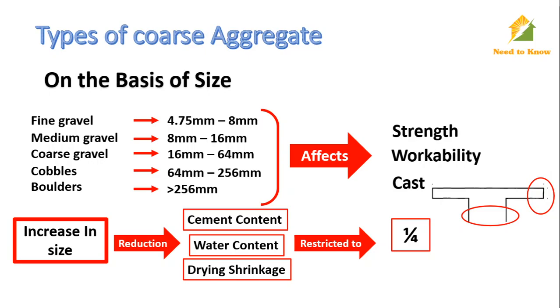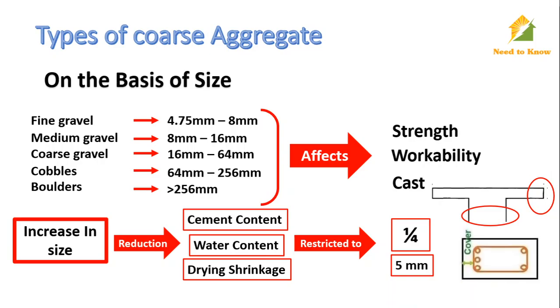The size of the aggregate should be less than one-fourth of the minimum thickness of the structural member. Secondly, the size of the aggregate must be five millimeters less than the minimum cover to the reinforcement.